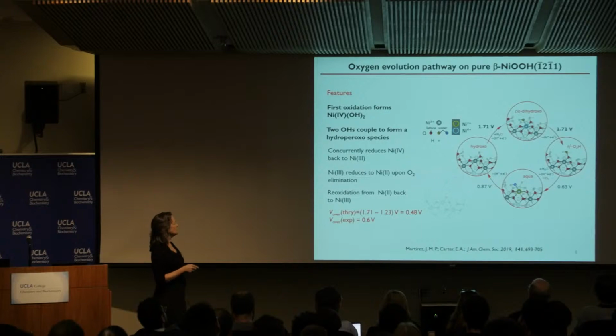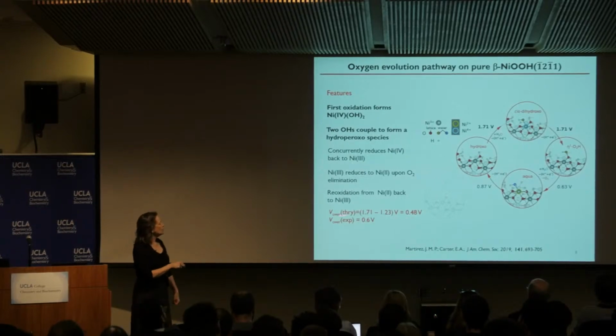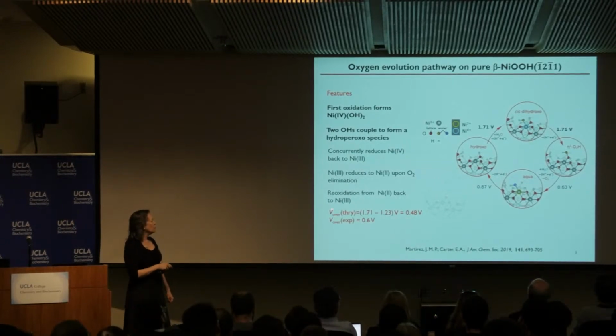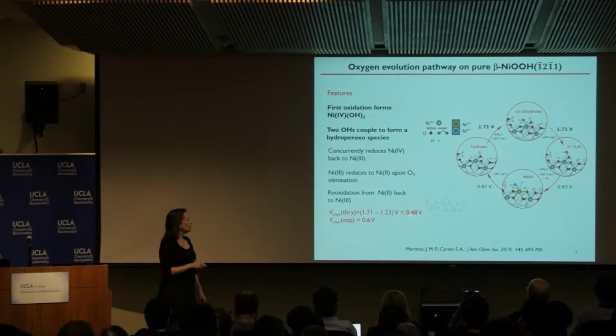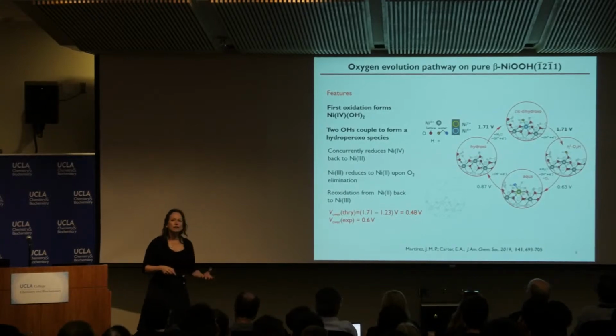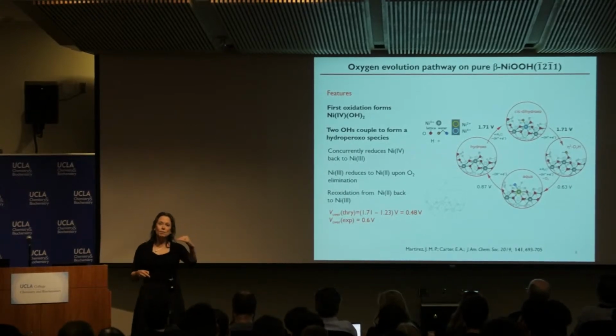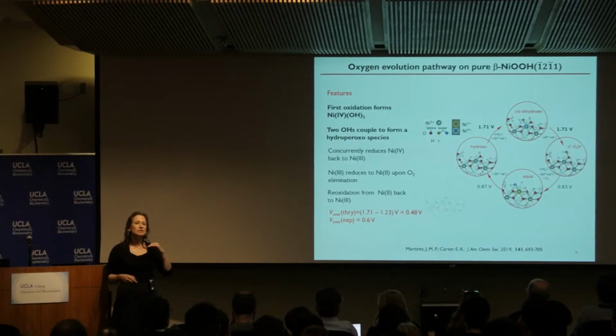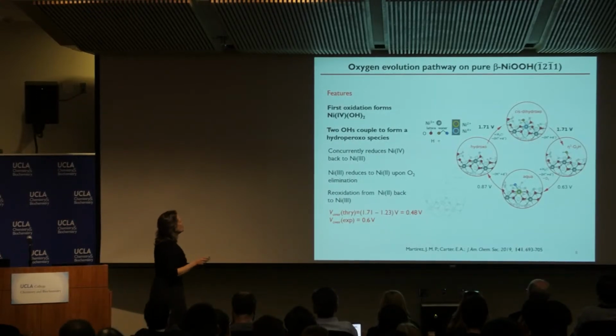And I won't go through the details of that, except then what we can do is, again, look at what we end up finding in terms of the overpotential. Well, Mark calculated an overpotential of 0.48 volts. Again, experimentally, it's 0.6 volts. So we are at that lower bound. So it gives us great confidence that we actually have nailed the mechanism.